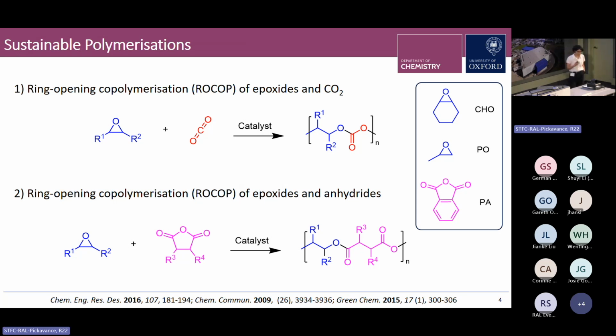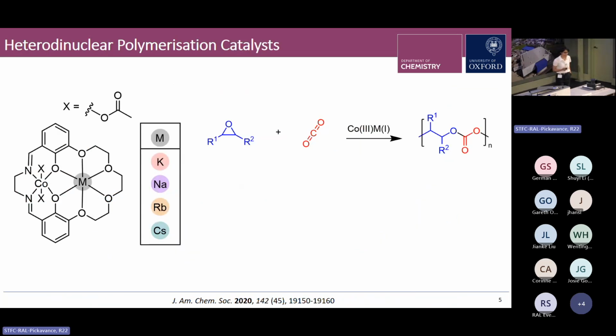But in order to achieve the fast, controlled, and selective synthesis of polymers using these monomers, a high-performance catalyst is essential. That's really the focus of this presentation. So in our group, we look at these well-defined homogeneous molecular catalysts that are heterodinuclear. So they contain binding sites for two metals that are different. And recently, we've been looking at this kind of macrocyclic ligand, which contains a Schiff-base binding site for a transition metal like cobalt and a crown ether binding site for a group 1 metal.